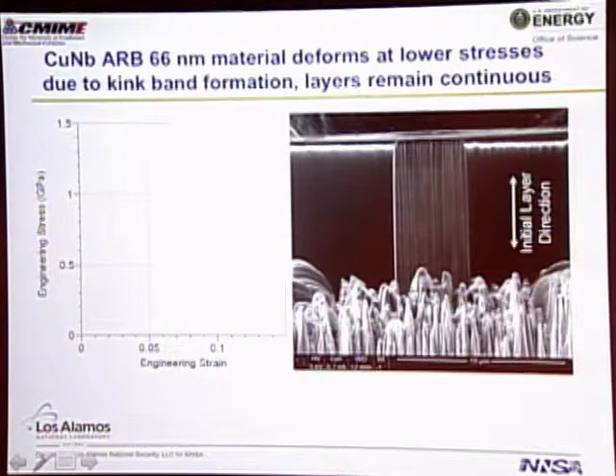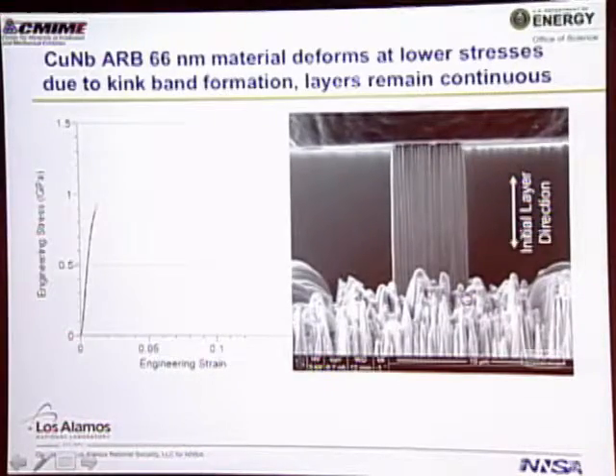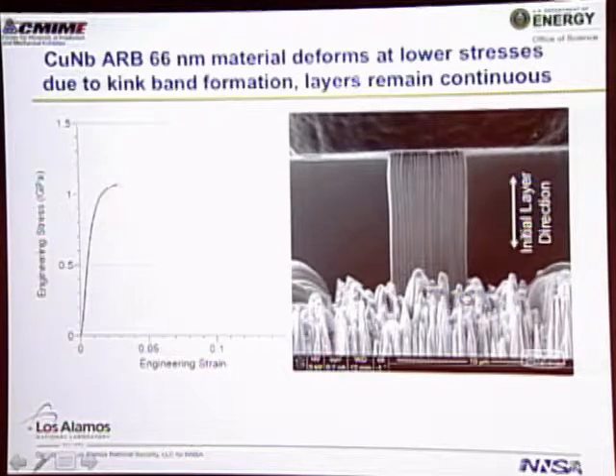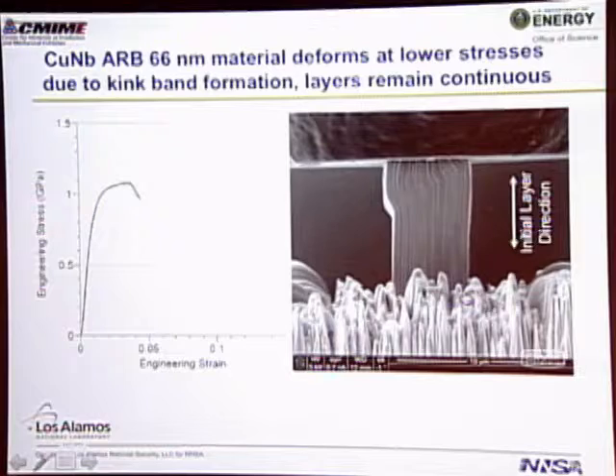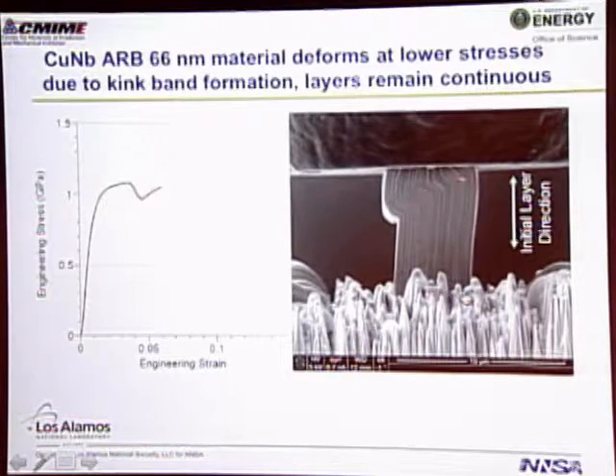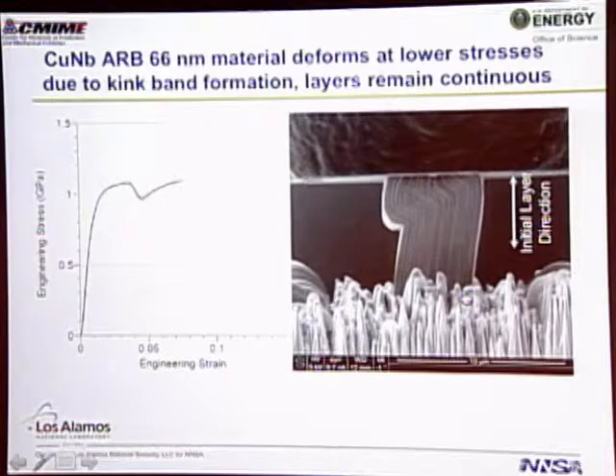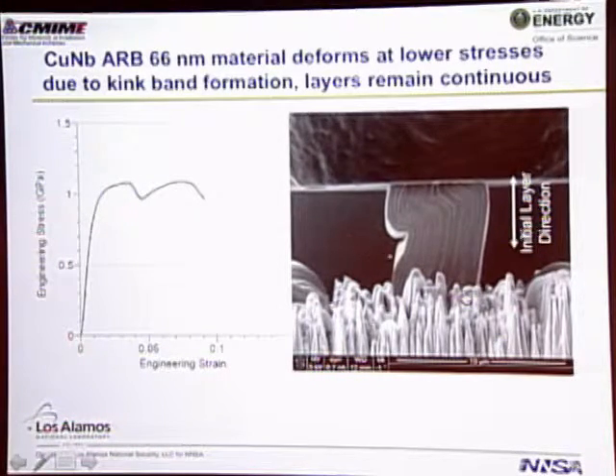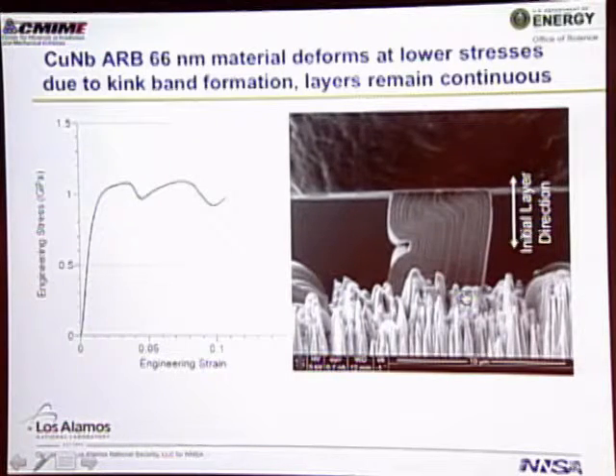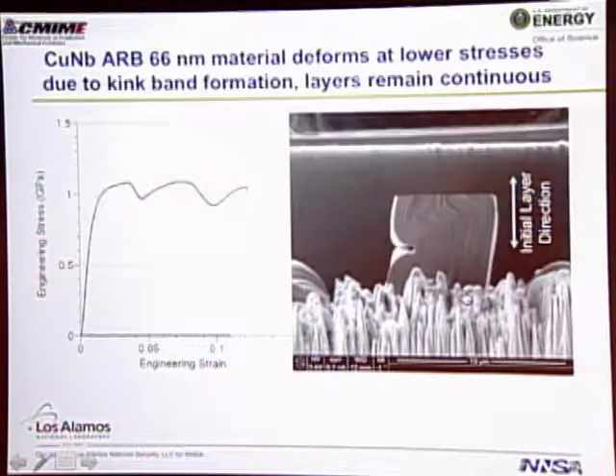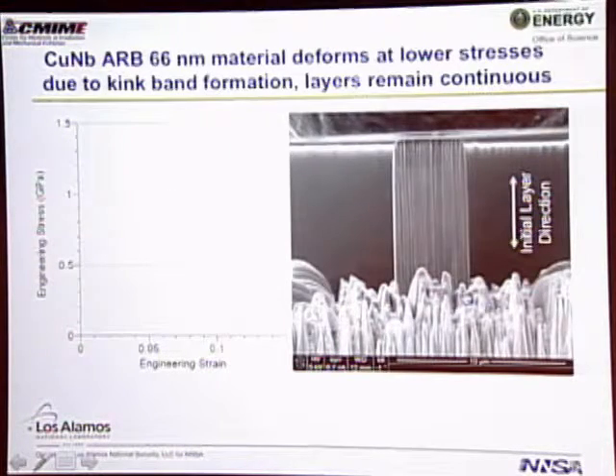Now let's look at that roll bonded type of material. You can actually see some of the layers have been kind of etched in the roll bonded material by the machining process that we use to make these. But what you're going to see is a very different kind of behavior. So we start loading it, we see the material starts to yield, you see some deformation, and then there's this load drop, and it corresponds to forming this band. It loads back up, it's going to show another load drop, and that corresponds to this band forming. So this kink banding mechanism allows us to deform this to very large strains without ever breaking the material. The material certainly becomes kinked and it's deformed locally, but it doesn't actually fracture.